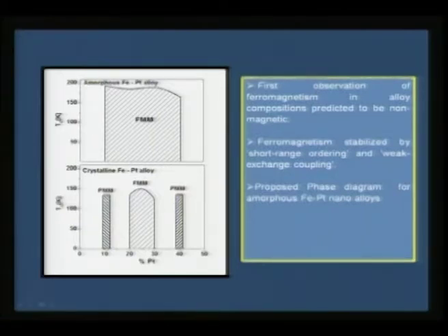So, in the crystalline alloy, this is a paramagnetic metal. In this phase it is a ferromagnetic metal, in this phase it is a paramagnetic metal, but in our study we can show that the entire region, from 10 to 40, is actually turning ferromagnetic metal. This is the beauty of studying the amorphous phase, and we can even go one step further to say that this is the first observation of ferromagnetism in alloy compositions which are predicted to be non-magnetic.